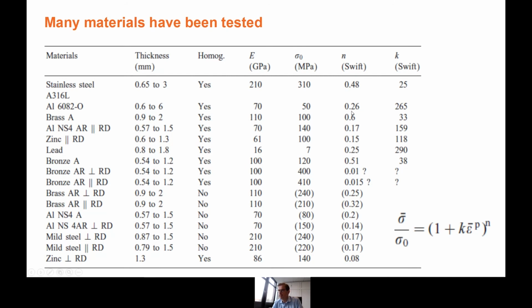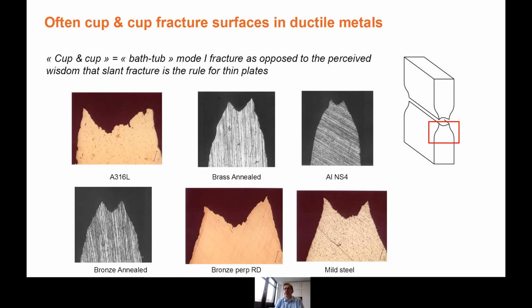Why is it stuck? Okay. Let's look at the fracture surface of all these materials. We always find a cup and cup profile. So what you see here is a section, as you see on the right. So the thickness direction here, and the fracture surface has always this curved shape. And as a matter of fact, if you take the other specimen on the top, it has exactly the same shape. So it's not at all a slant fracture.